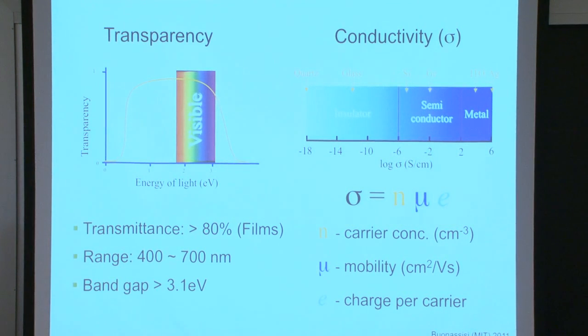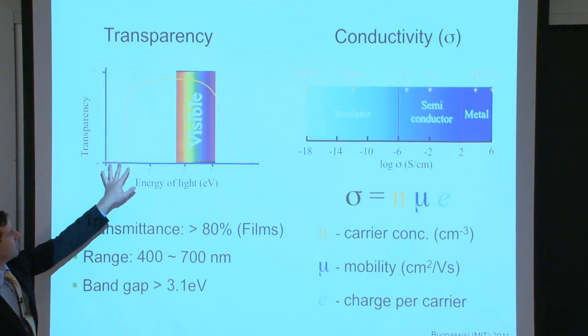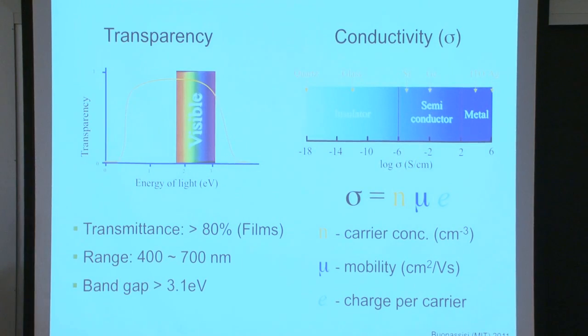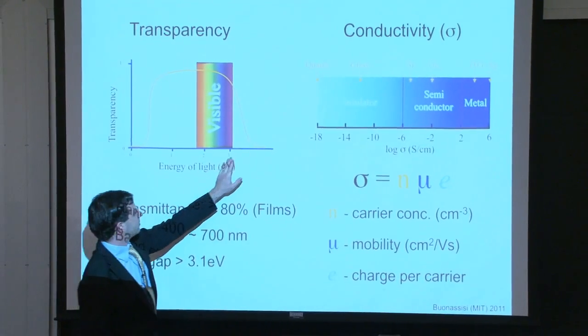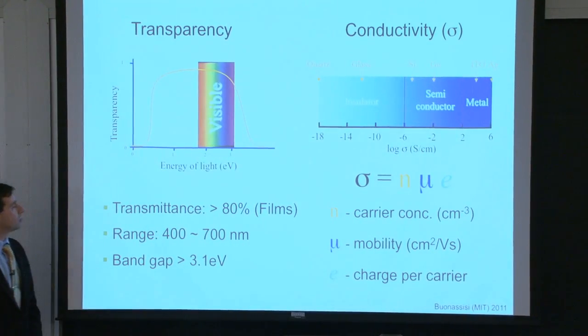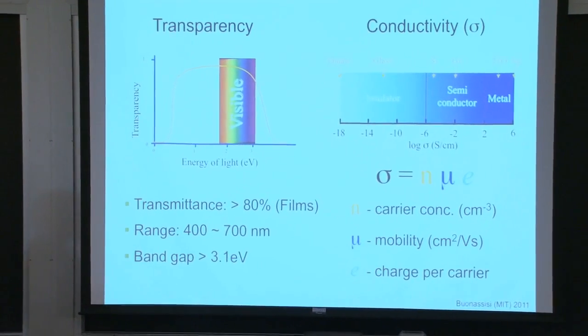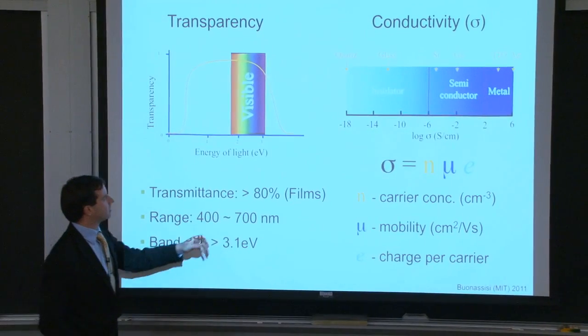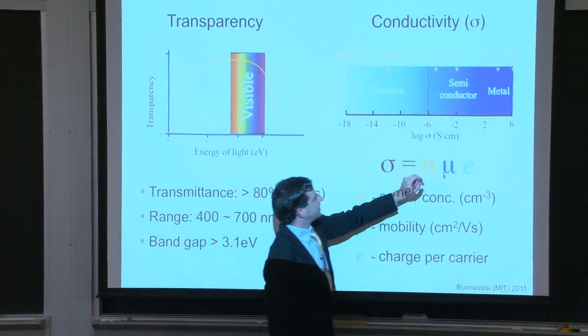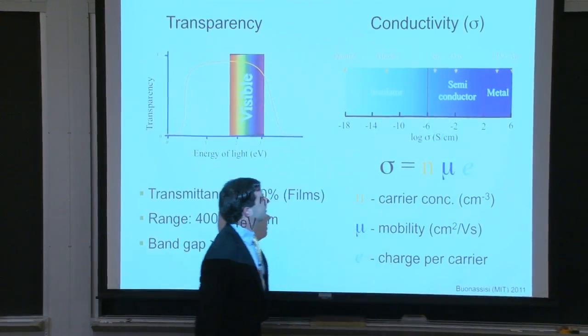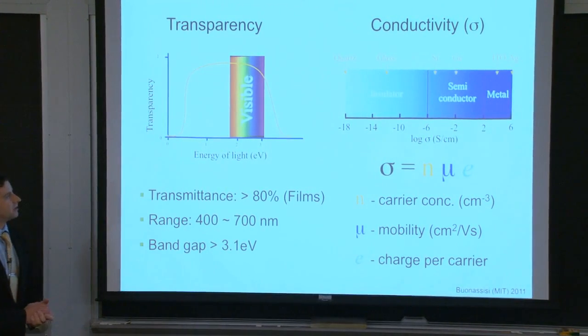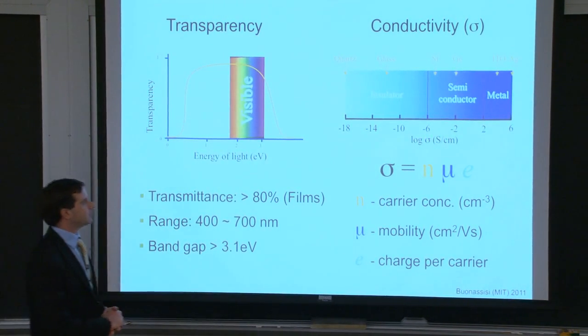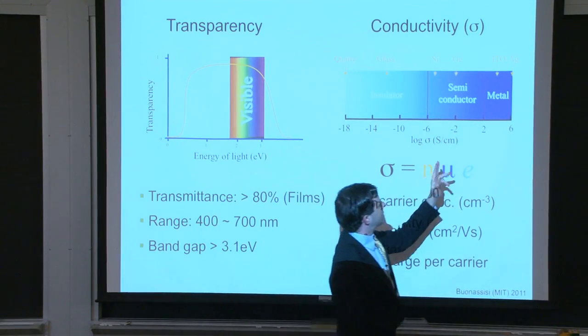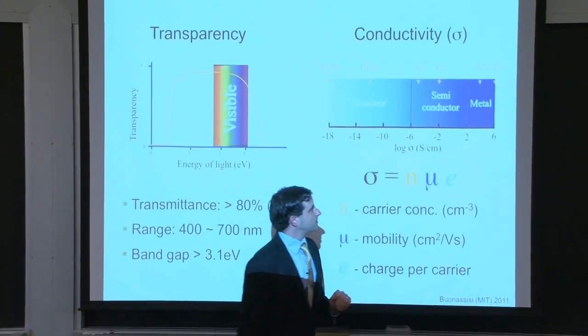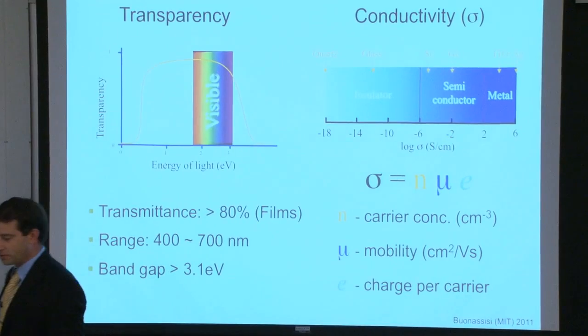So the material is very transparent. You can see the transparency over quite a broad wavelength range here. Cutting off only in the several eV range here, the transparency begins to drop because you're able to excite carriers across the band gap. So it's a very large band gap material. And yet the conductivity is very good. So here we can see that the conductivity of ITO, that's indium tin oxide, that's a particular type of transparent conducting oxide, is almost as good as silver. Not quite, but it's approaching it.